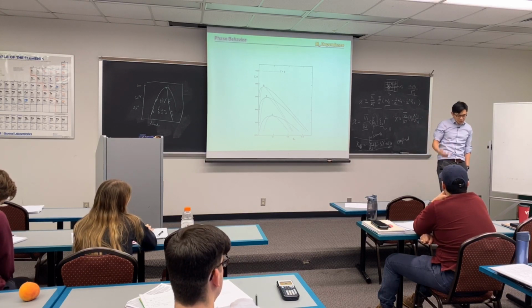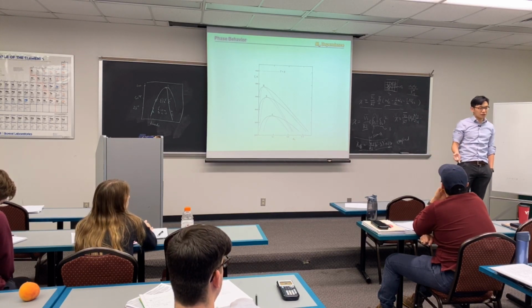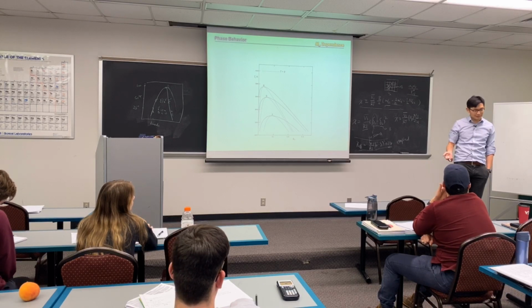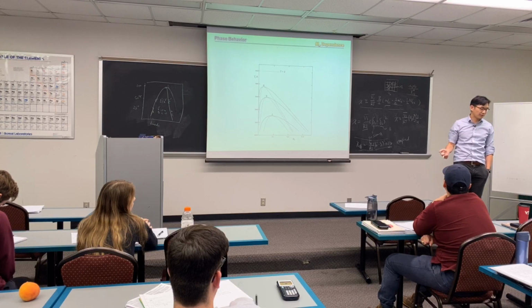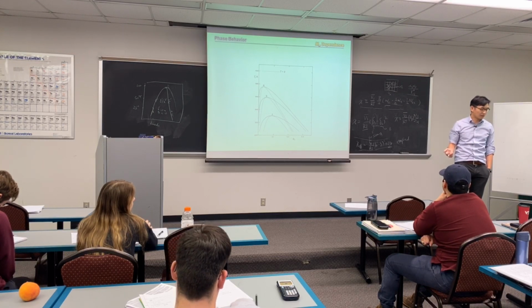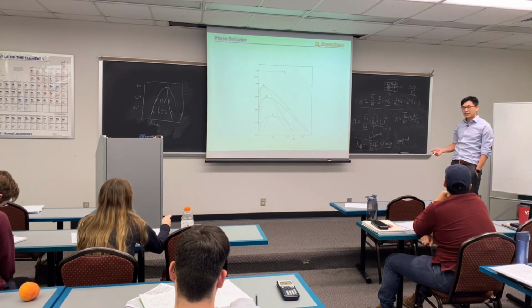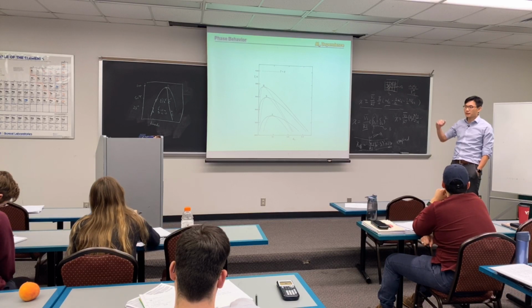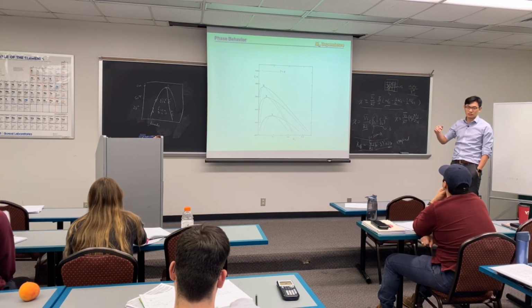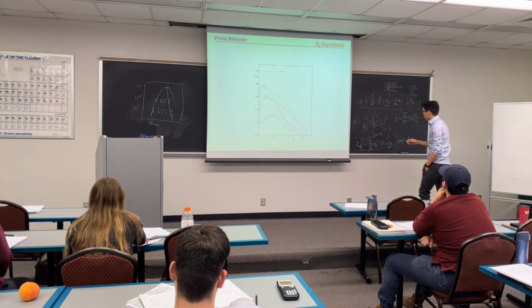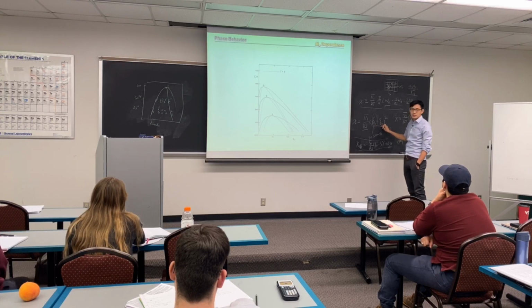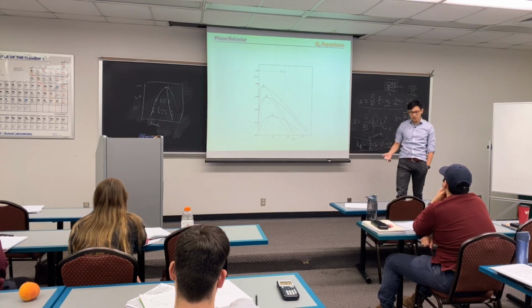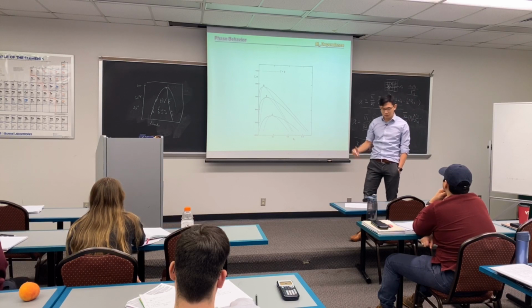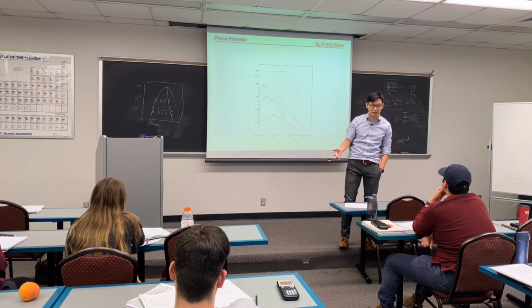But chi equals 0.5 is an interesting value. 0.5 is where you have theta solvent. Okay, I want everybody to understand that. And when the chi goes up, that means there's more unfavorable interaction, and that's counted by the solubility parameter difference. If your chi is very large, that means your two materials are less likely going to mix.